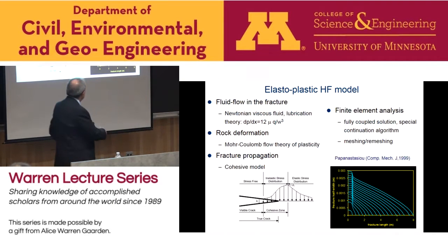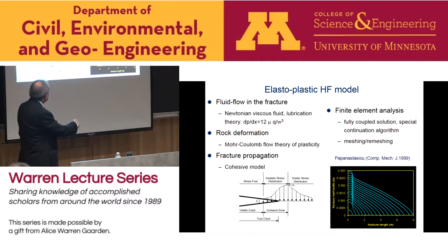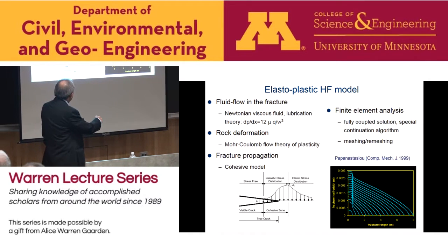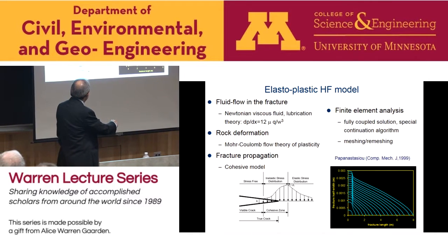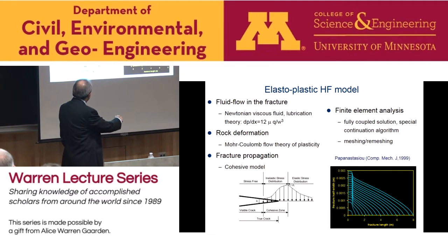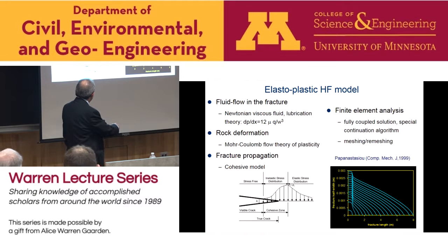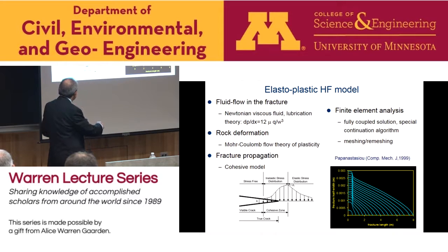To investigate that, we set up an elastoplastic, fully coupled hydraulic fracturing model. We took into account all the processes in a coupled manner: the fluid flow in the fracture, and the rock deformation for weak rocks, using plasticity theory and Mohr-Coulomb. And we also use a good, robust fracture propagation criterion based on the cohesive model.